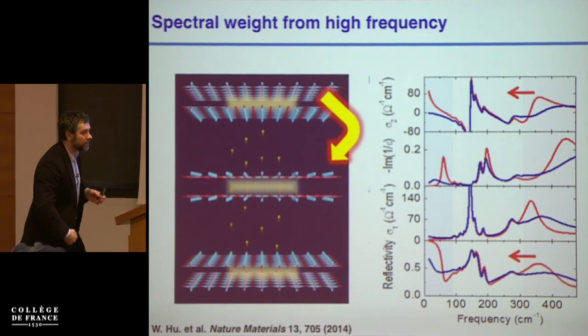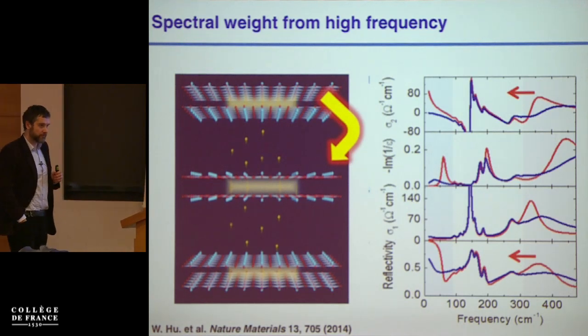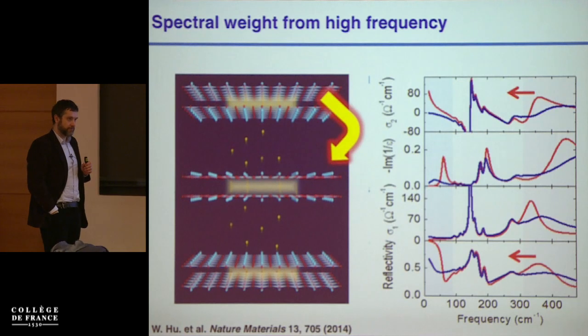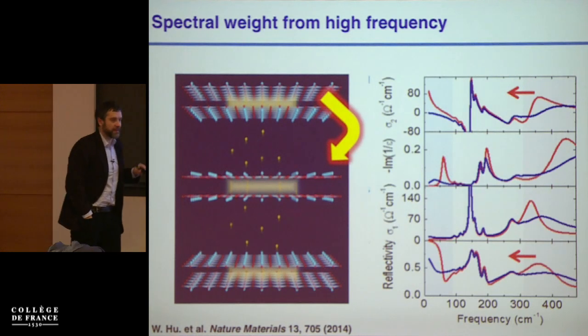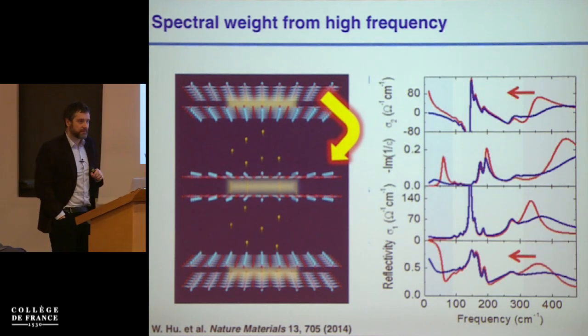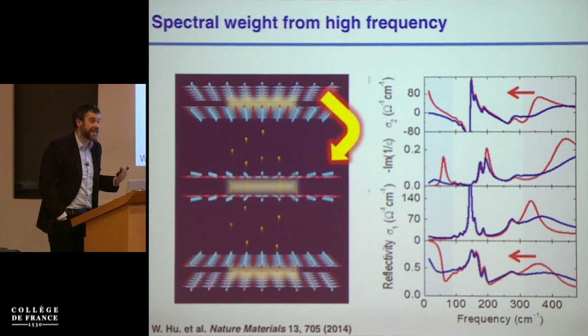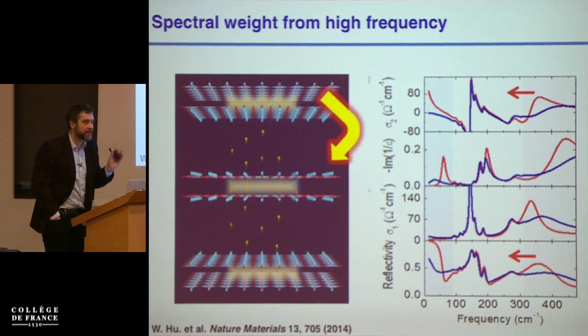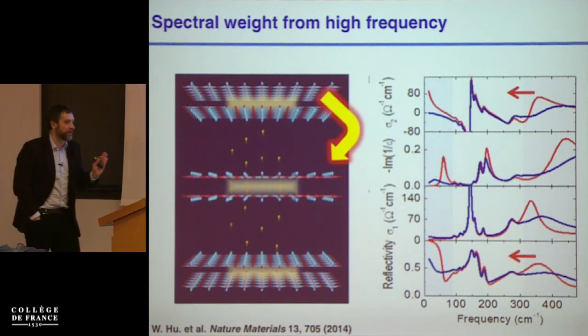Yes? No, but I didn't get exactly the point about the in-plane sigma 2. What happens to in-plane sigma 2 when you do this above TC? Nothing. Oh, above TC, also nothing, pretty much. Seriously? Yeah. Well, at least nothing in the sense that we weren't able to see anything, which are two slightly different statements, but to first order 0, right?